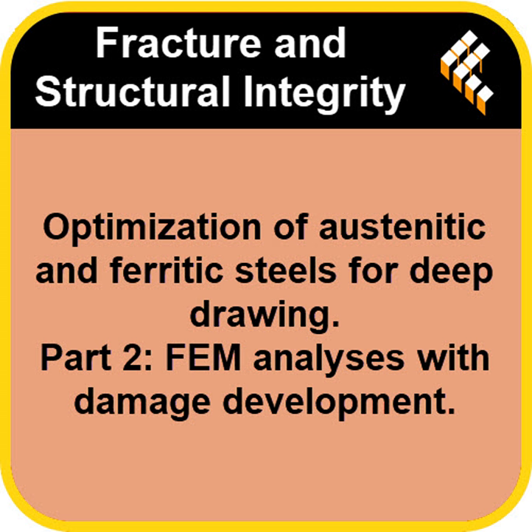It really is. Yeah. And crucially, the simulation didn't just get the number right, it also visually replicated the failure modes. It correctly predicted the double bell strain pattern and intermediate failure without lube, and the single bell pattern with apex failure when the PVC lube was simulated. So the model captured the fundamental physics. That predictive power is huge.